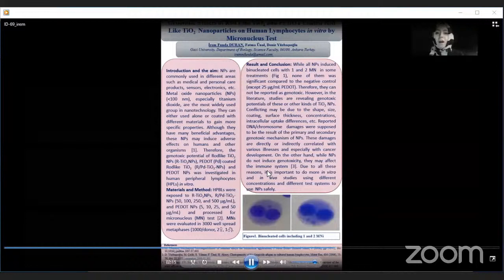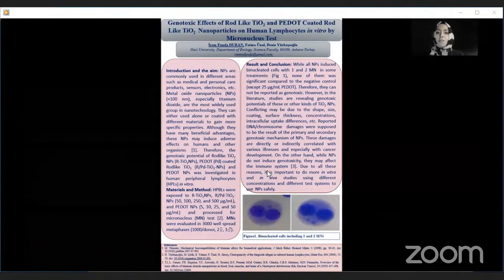However, in the literature, studies are revealing the genotoxic potential of this or other kinds of titanium dioxide nanoparticles. Conflicting results might be due to size, coating, surface thickness, concentration, and intracellular uptake differences. Reported DNA or chromosome damage was supposed to be the result of the primary and secondary genotoxic mechanisms of nanoparticles. These damages are directly or indirectly correlated with various illnesses and especially with cancer development. On the other hand, while nanoparticles may not induce genotoxicity, they might affect the immune system. Due to all these reasons, it is important to do more in vitro and in vivo studies using different concentrations and different test systems to use nanoparticles safely.